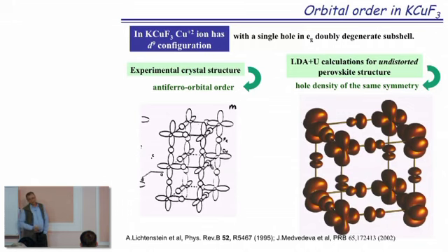And that is the result of our LDA+U calculation for the same property. We have just drawn space distribution of hole. Important is the following. We have chosen non-distorted structure, because if it will be distorted, then orbital order is just enforced. No, it is undistorted structure. And orbital order has appeared from electronic degrees of freedom only. And then lattice will react parasitically and distort.